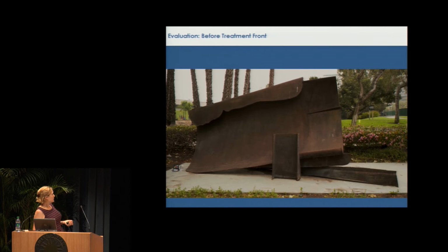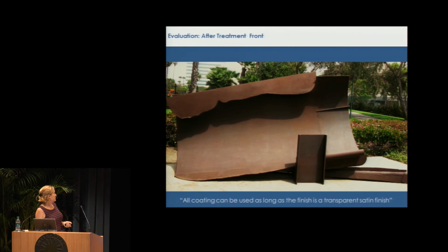Here you can see again the sculpture before treatment, and this is the sculpture after treatment. In the end, it turned out really nicely, except for here, where you see where the Paraloid coating was. That coating must have gotten into the corrosion layer and had a very strong bond, so I couldn't remove that coating. So you really have a darker area here and this area, and then on the backside there was also an area where you have a darker coating.